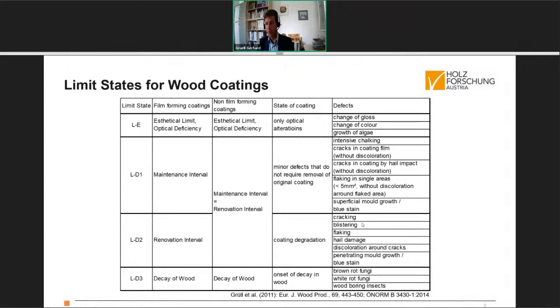Then there is a renovation interval when cracking, blistering, flaking, and so on occurs in a larger extent, in particular that the adhesion of the coating is lost, which needs removal of the old coating film and layup and application of a new coating system, starting from the impregnation in most cases. And there is another level, a fourth level, on durability of the wood. This is the decay of wood. This is the case when brown rot and white rot fungi or wood-boring insects have attacked the wood. This needs completely different work in restoration of buildings and building parts, which is beyond the degradation of the coating itself.